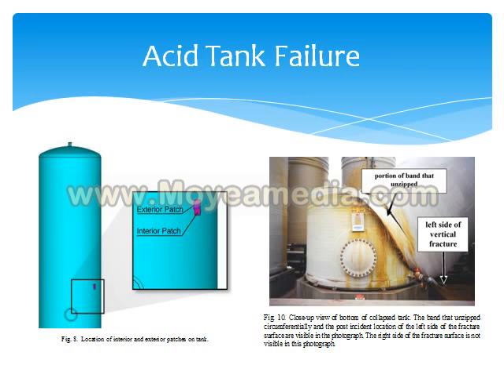Here you can see pictures of a fiberglass tank which was patched incorrectly with a non-acid resistant inner layer, and this resulted in decreased fracture toughness under the heavy loading of the acid and ultimately the failure of the tank.